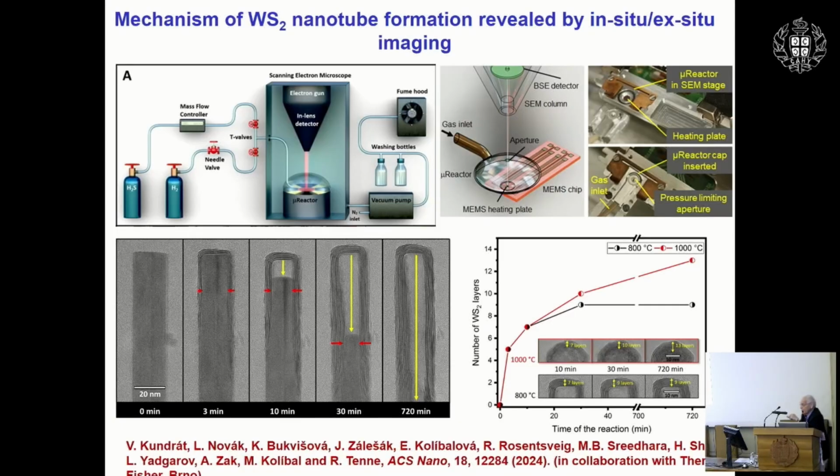So this is the first time that you can really show that you can do a microreaction in the electron microscope. Within the electron microscope, you can take this stub or this grid from the SEM to the TEM and look at the high resolution reaction at every step and how the reaction is progressing. And I won't go into the details, but we have actually promoted here a new growth mechanism for the nanotubes.